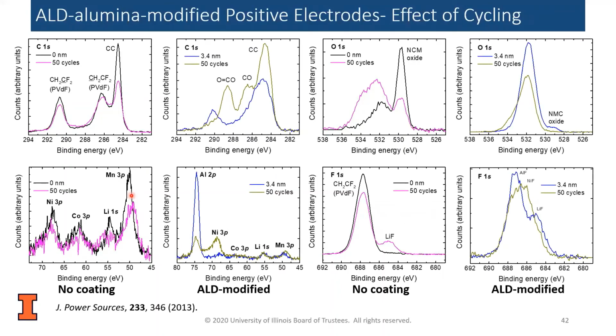And this is a comparison with, so this was an uncoated, this is coated. So before and after 50 cycles. And so one thing we can notice that's very, very interesting is that the chemistry of the coating is different. We see that in the alumina coated material, we have a pretty intense carbonyl signal that we didn't really see in the uncoated. So it indicates that the chemistry of the surface of the material is actually important in terms of the behavior and the performance of the battery.